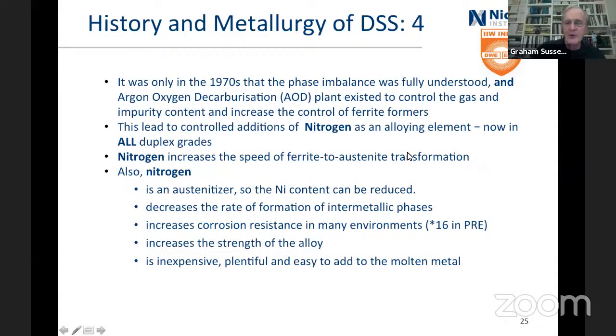It increases the speed of the ferrite to austenite transformation, so you don't have to be quite so bothered about how quickly it's cooling down above 1000. And also nitrogen is an austenitizer itself, so the nickel content can go down, which is good because nickel's expensive. It decreases the rate of formation of intermetallic phases, increases the corrosion resistance, that's the 16 in the PRE formula, and increases the strength, you saw that on that first chart.